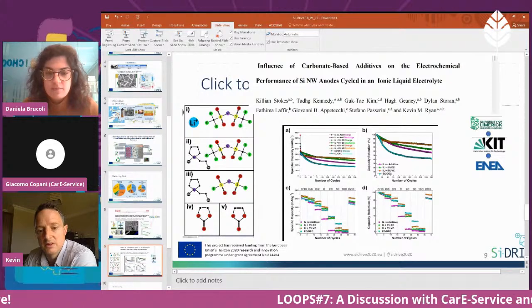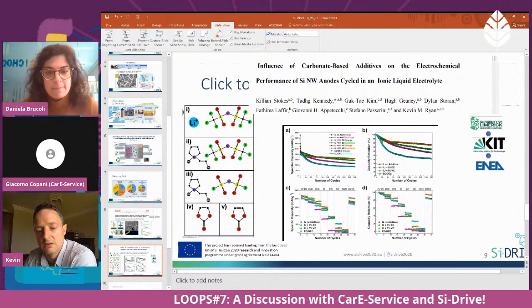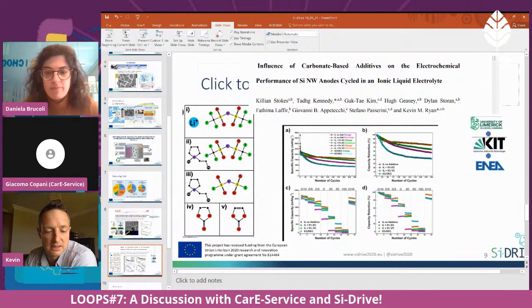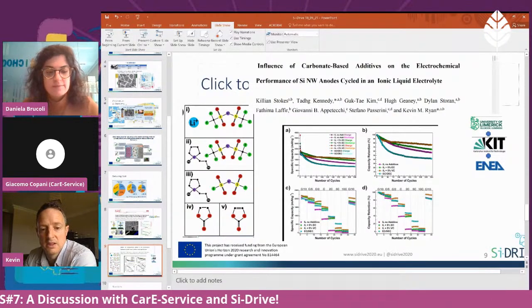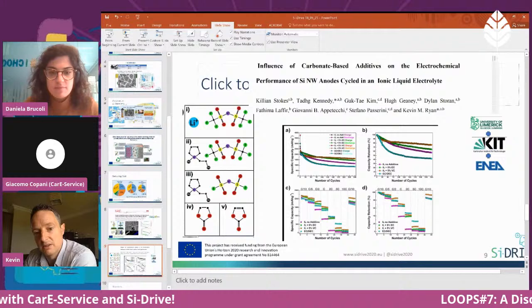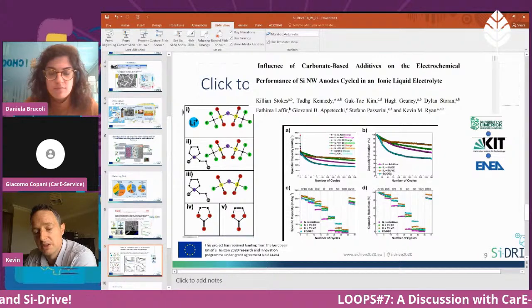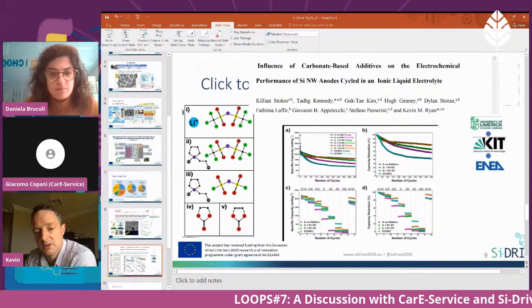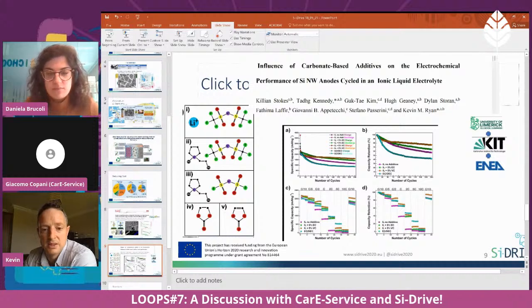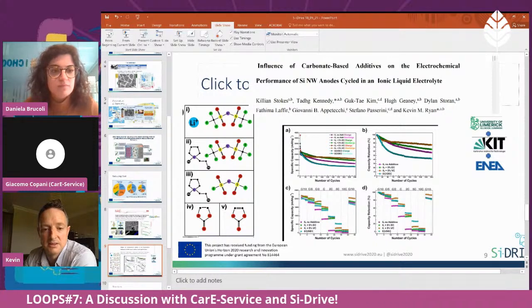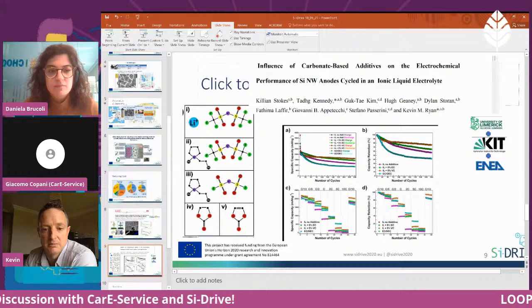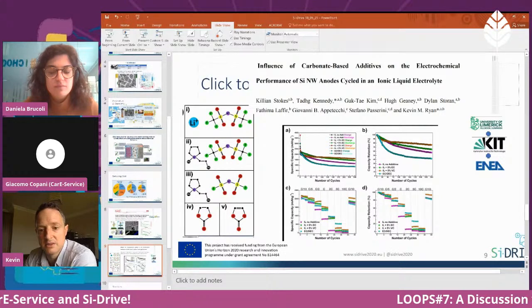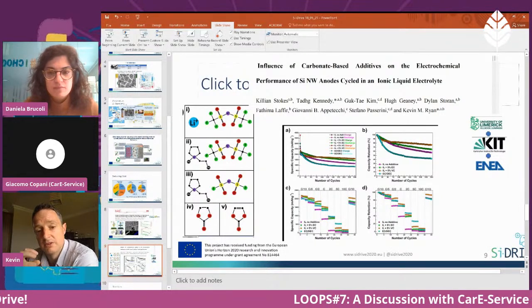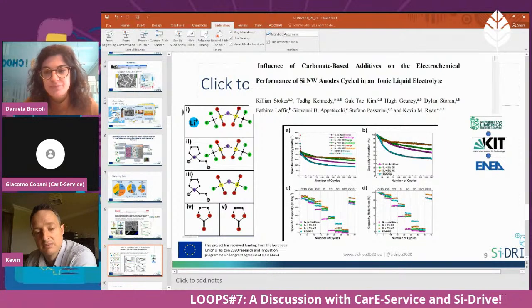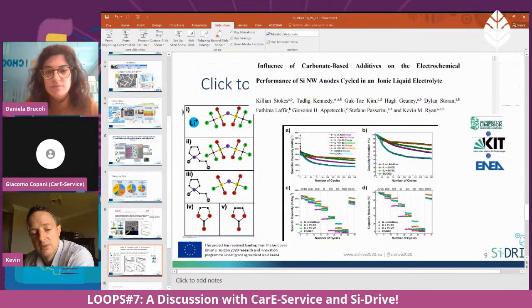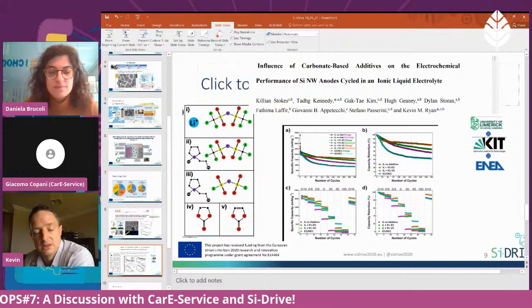And what we found was that if you add a small amount of additives, such as ethylene carbonate or vinylene carbonate, to the ionic liquids, this provides enough material to allow for a degradation to form a stable SEI. We're only talking about 5% here. And then with, for example, the vinylene carbonate and the ethylene carbonate, these form a very flexible SEI layer on your silicon nanowire anodes, which allows you to get very stable cycling.